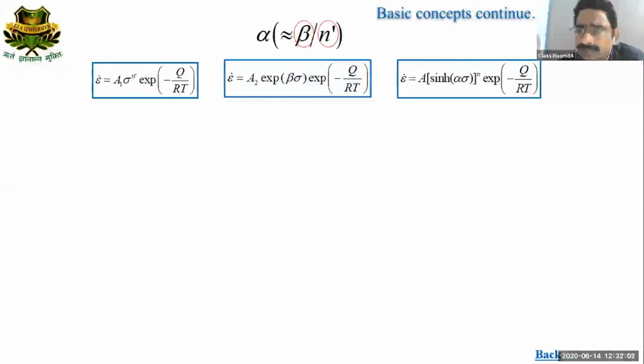Yeah. Fine. Okay. So another question I am having, while developing this processing map, you have mentioned that during the experiment you have used the thermocouple to measure the temperature of the specimen, isn't it? So have you done the adiabatic temperature correction? I have done. In one flow stress curve, you have seen one dotted curve was there. Those dotted lines are adiabatically corrected flow stress, and I have also told that I am not going into the detail of adiabatic correction, but we have done all adiabatic corrections.